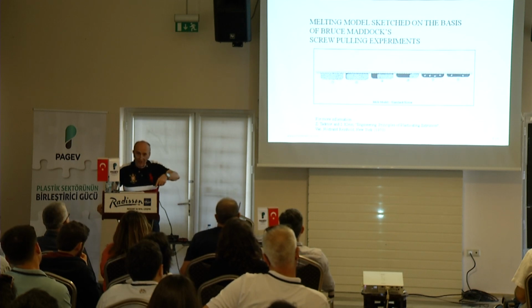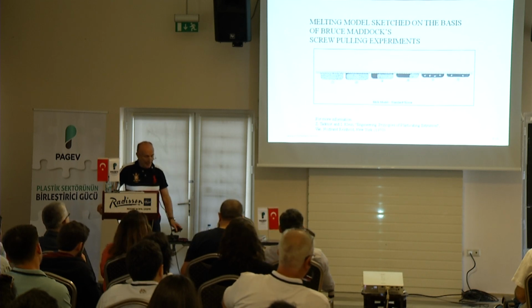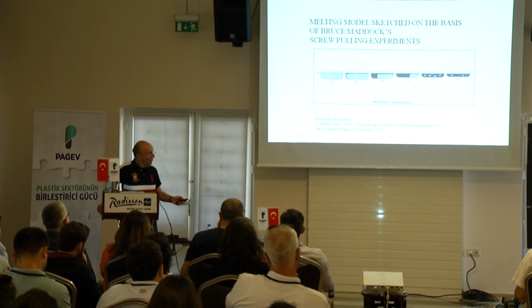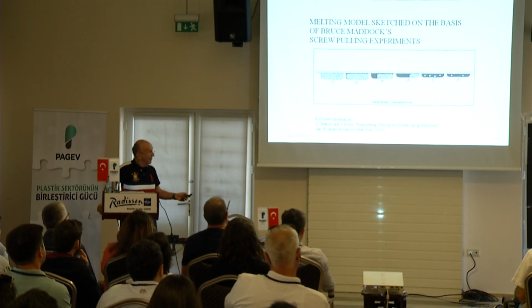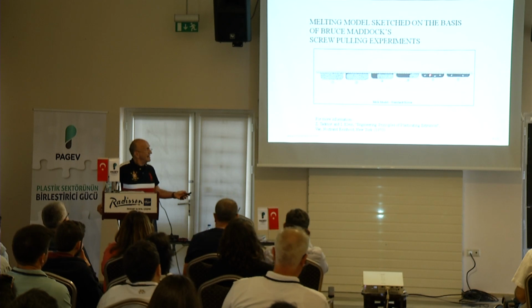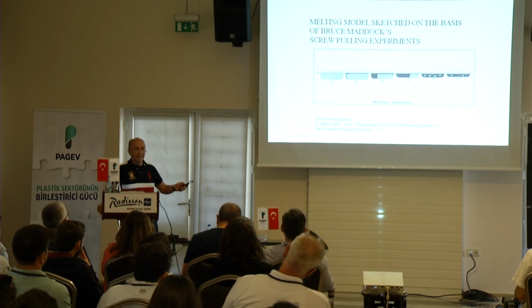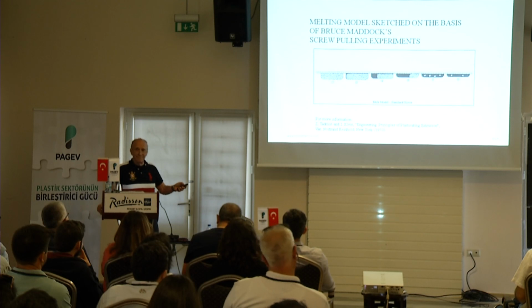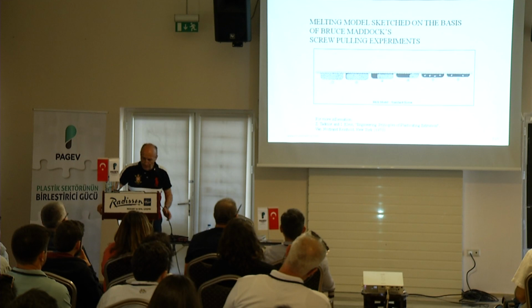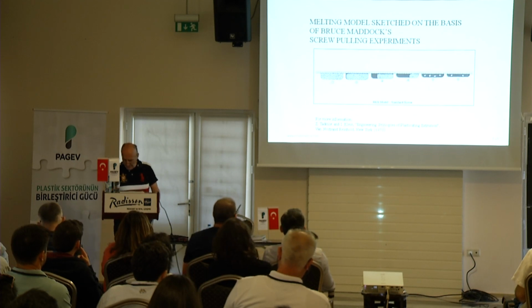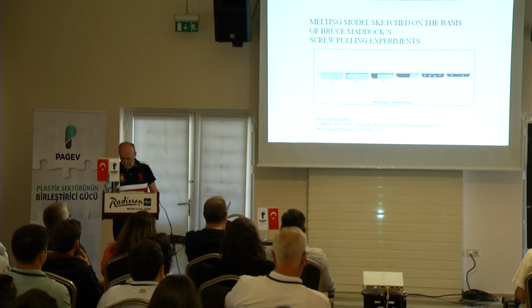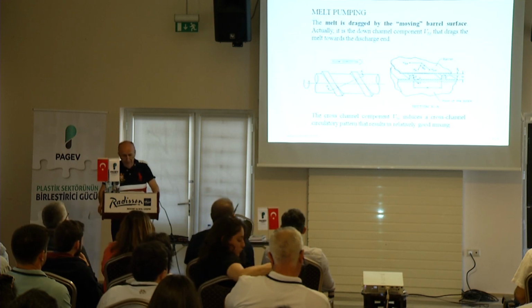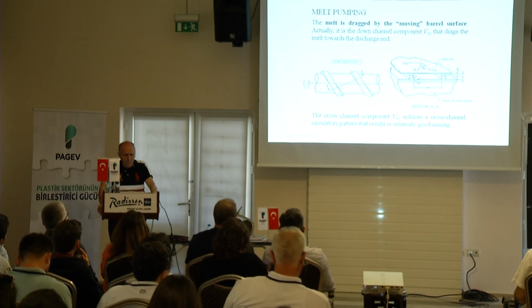I'm going to show you results. I have actual experiments that I'll show you. And this is bad news. So we don't want this to happen, because these particles float in the melt and they just never melt. So you really need shear in order to have an effective melting machine. Well, the melt pumping then is what I mentioned.